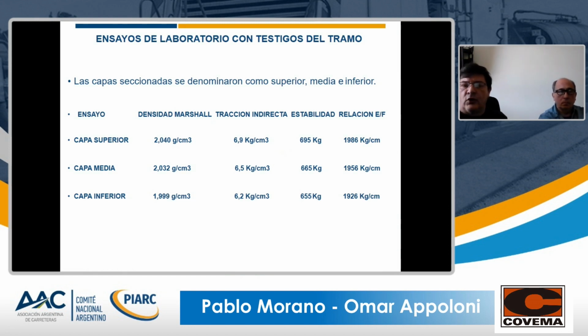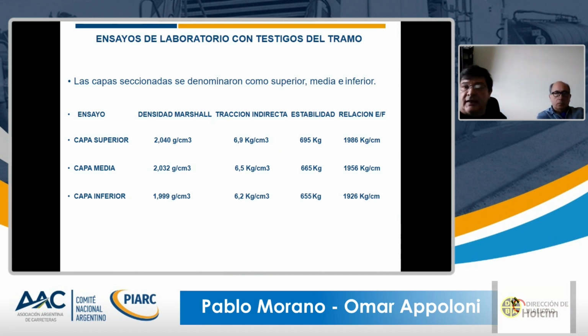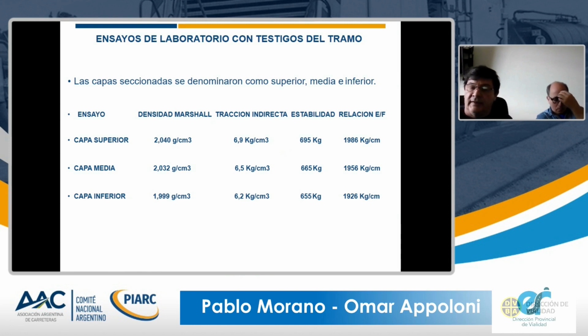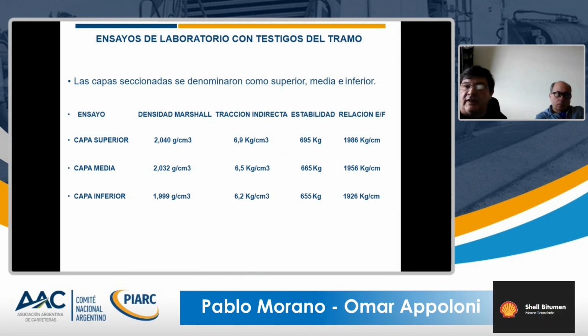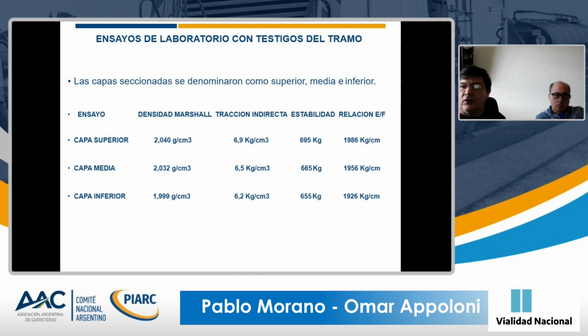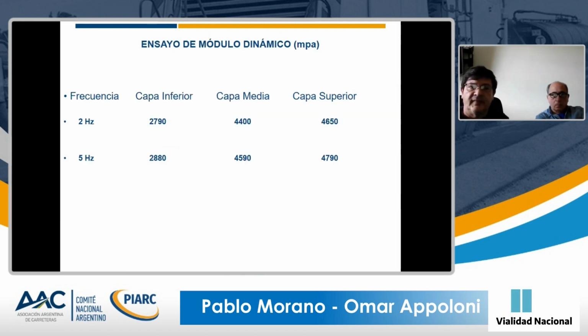The density was not altered, and it was maintained despite compaction. We had a density that went from 1.999 to 2.040. Indirect traction, that is one of the parameters that we evaluate for these indirect measurements, behaved very well. It was above 6, going from 6.2 in the bottom sample and 6.9 in the top sample. Stability was from 650 to 690, and the fluency was around 1900.